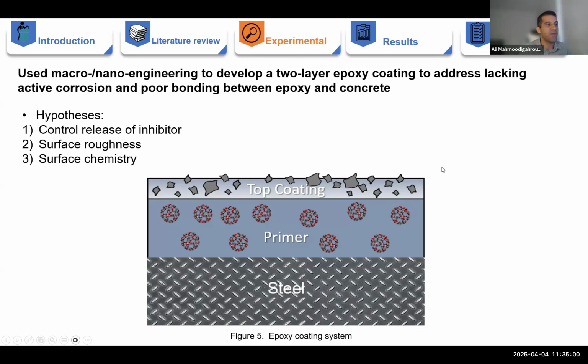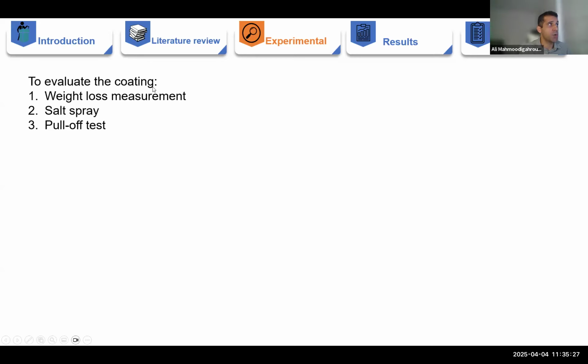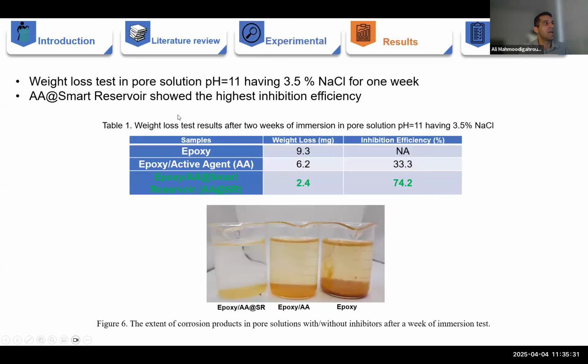And for top coating, we hypothesized that if we can apply some abrasive materials like bone ash, like crushed glass, we can change the surface chemistry from hydrophobic to hydrophilic. And then we can also introduce some texture. We can make the surface rough, and we can improve bonding between coated rebar and concrete. To evaluate our coating, we used weight loss measurements, salt spray, and pull-off test.